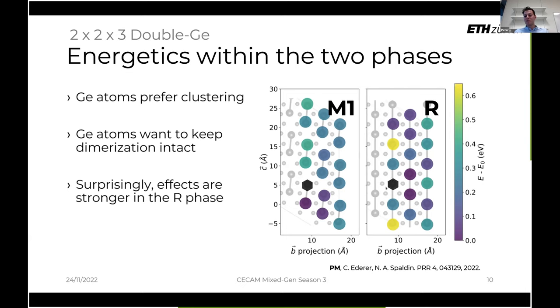But then of course, if we keep one germanium in one chain and add another germanium in a separate chain, these arguments become a bit more muddy. That's why I didn't really want to go there, because the whole structure is quite disordered. So it's not really clear to say that if we add a germanium here and another germanium here, how exactly do dimers form, or does this contribute to dimerization or does it not? So. Okay, thank you.